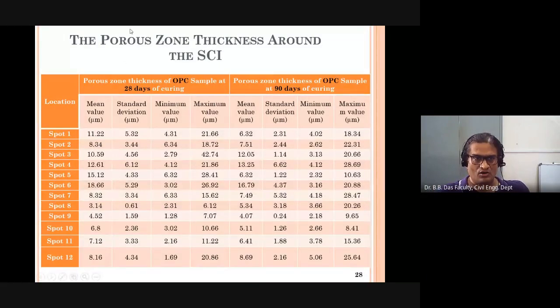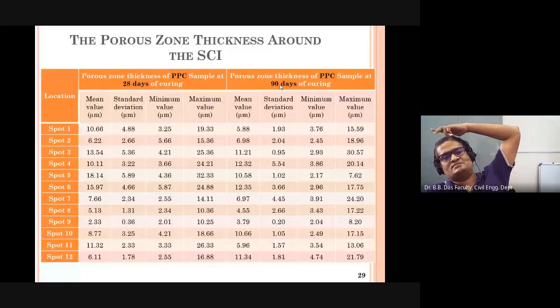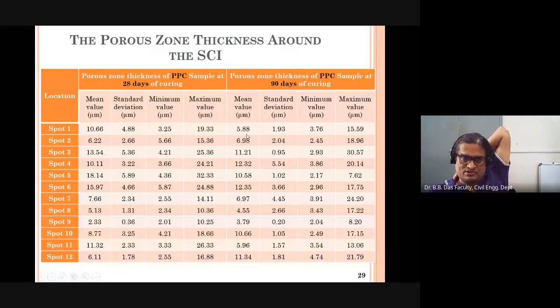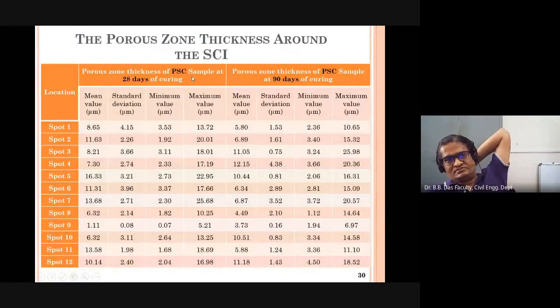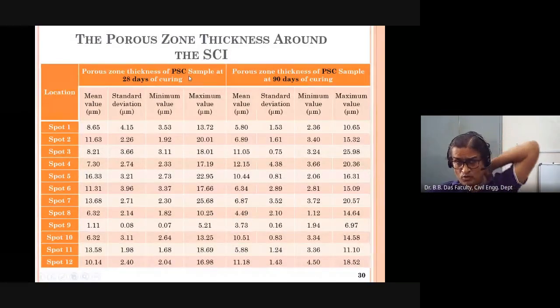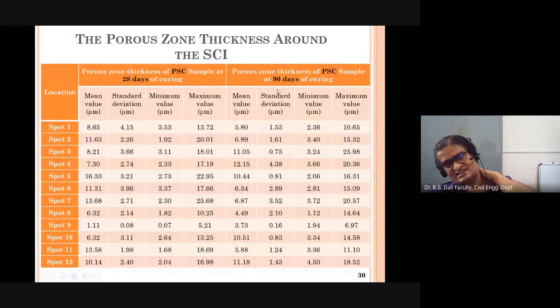Like that, all of these are 30 measurements, with mean value, standard deviation, minimum, and maximum. Now we have to consider the mean values. This is my 28 days, and this is my 90 days. Similarly, this is for the PPC sample, 28 days and 90 days, same mean values. And this is my PSC, Portland Slag Cement, 28 days and 90 days.